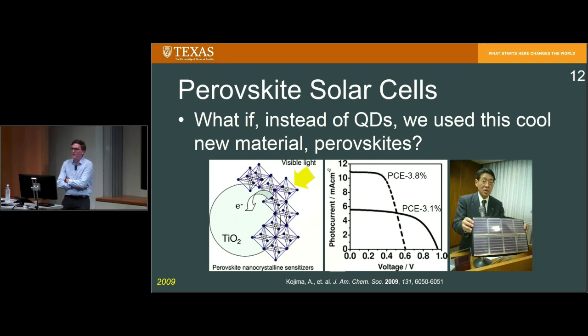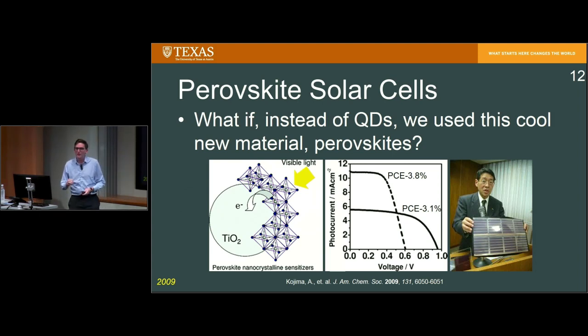But it was around the advent of the quantum dot solar cell that people were trying to say, okay, we have really bad efficiencies. Where can we find new materials to put in this architecture that are going to change things, make them better? And one researcher in Japan, Professor Tsutomu Miyasaka, said that, okay, well, I have this semiconducting material, these methyl ammonium lead iodide perovskites, that I can dissolve in dimethylformamide. What if I don't want to make quantum dots using the traditional methods, hot injection methods and the like, but what if I can make a quantum dot solar cell by dissolving this material, putting it on TiO2, and just letting it react on the TiO2 and see what happens? And he actually was able to get 4% efficiency from the first trials that he performed in his lab.